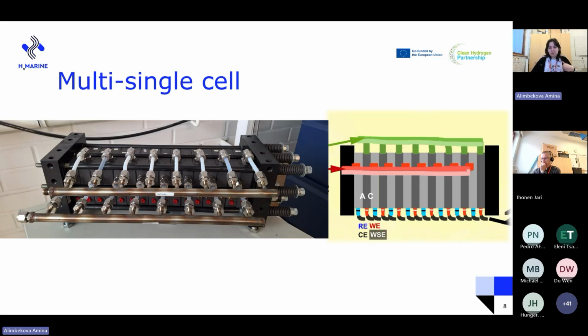Therefore, if some kind of disturbance occurs during a 100-hour maritime cycling run, it will affect all cells evenly, especially under hydrogen-nitrogen mode, because no water is being produced and the flows are selected to be strong enough to not cause any flooding. By fixing these environmental variables across all 8 channels simultaneously, we can isolate these experimental variances to the components themselves.